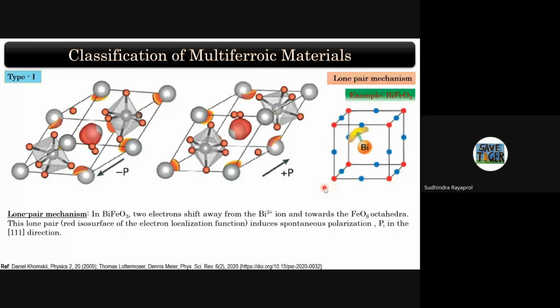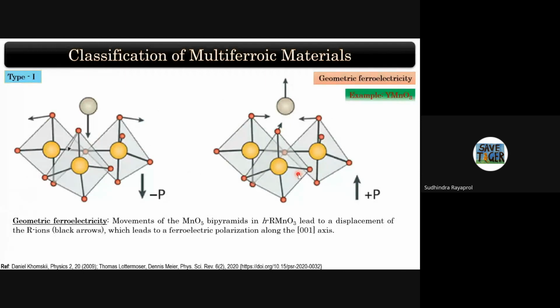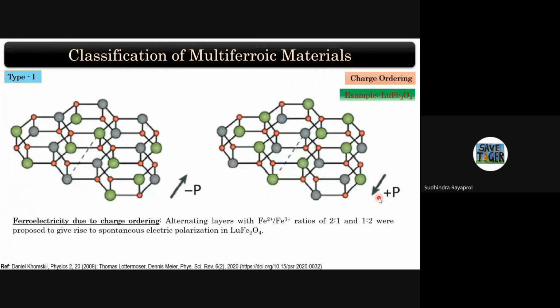Now, if you look at the classification of multiferroic materials, you have type 1 multiferroics like bismuth ferrite, where because of the shifting of the lone pair bismuth ions towards these oxygens, that causes the displacement of the polyhedra, and then that can give rise to spontaneous polarization in the system. You can have geometric frustration also, as we have seen. In this case also, the movement of these polyhedra or bipyramids can give rise to displacement, which can yield the polarization. You can have charge ordering also. Because of the charge ordering, there is a movement of these planes, and because of the movement of planes, you can have the polarization.